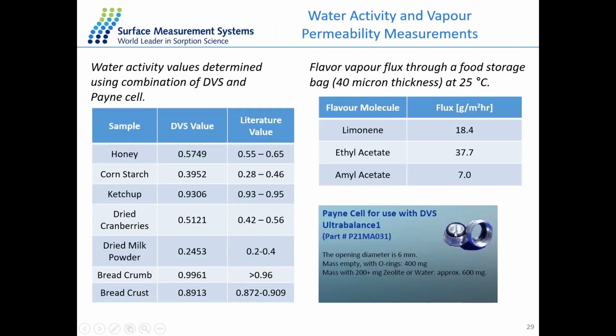And we can also use this Payne cell to study the water activity for the material by doing a calibration curve with the saturated salt samples. And then we can put the sample of interest into the cell, and then we measure the moisture or water activity inside the food material. So for example, here we get the result for the honey sample, the ketchup sample, as well as some milk powder, and it has really good agreement with the literature reported values.